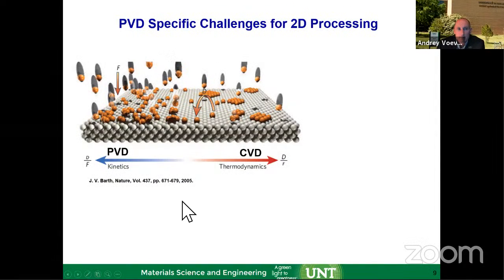Fundamentally, PVD is using high density flux, so you have high deposition flux and high kinetic energy. For chemical vapor deposition, you're using low density flux and low incoming kinetic energy, with high temperature. So in CVD, you're using the temperature for atoms to hop around, find a place and form the crystal, and that crystal grows. In PVD, you don't allow for that time. You bombard them with a lot of atoms. Those atoms have very short time to move around, and they're locked in place. If the temperature is too low, they will produce amorphous material. If the temperature is a little bit higher, you have enough energy, and they will form nanocrystals. They will rarely or almost never grow a single crystal unless the temperature is too high. So low temperature, that's what it is.